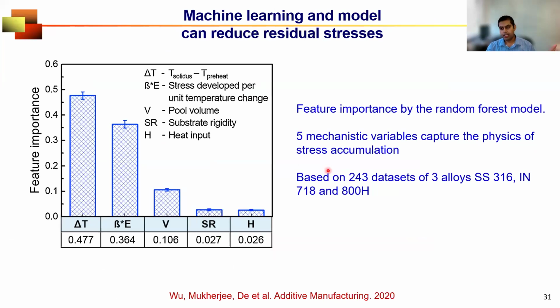Now, going back to one of the primary advantages of using machine learning. So that was to identify the relative importance of important variables. What we did, we identified 5 physical factors that control or affect residual stress formation. And we created a database of 243 data points for 3 very commonly used alloys. What we found, delta T, which is nothing but the difference between solidus and preheat temperature, is the most important